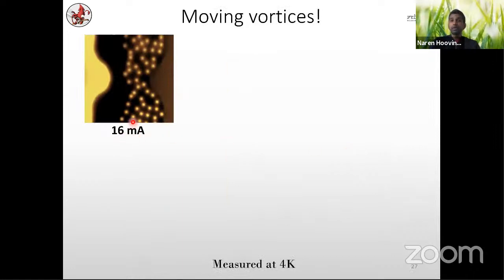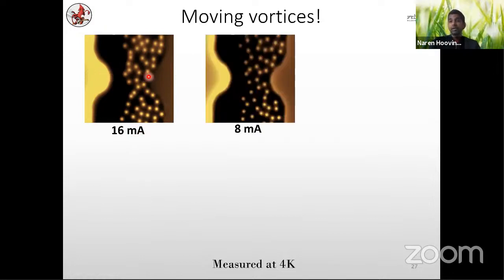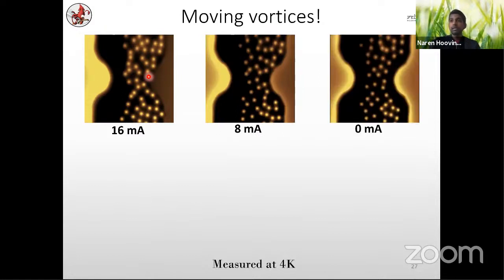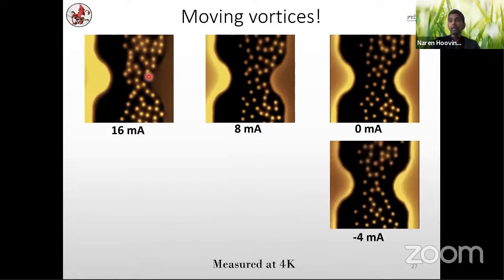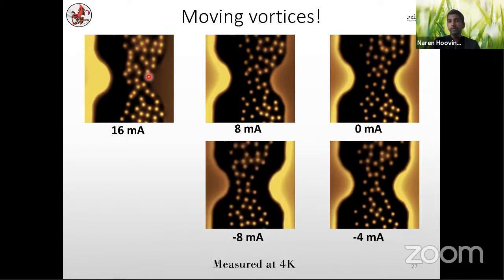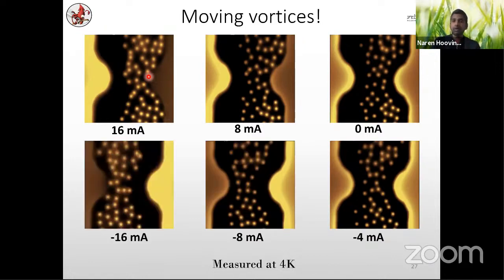For example, you apply a small current of 16 milliamps, and the vortices are all shifted to one end. Then you can reduce the current, and they relax back. You make it zero, but because of a phenomenon known as pinning in these materials, it does not exactly come back to the center. You need to apply a bit more negative current in the opposite direction, and then it comes to the center, and then you can move it to the other side. So basically you can play around with this field of view of the vortices by applying different currents.